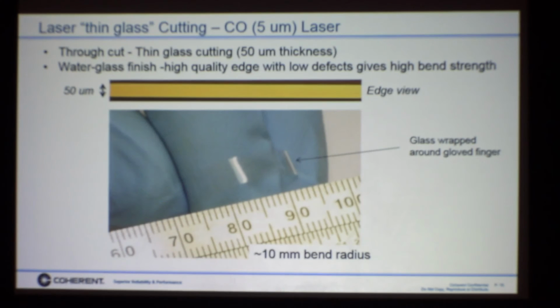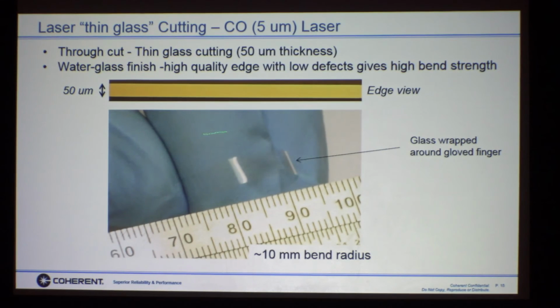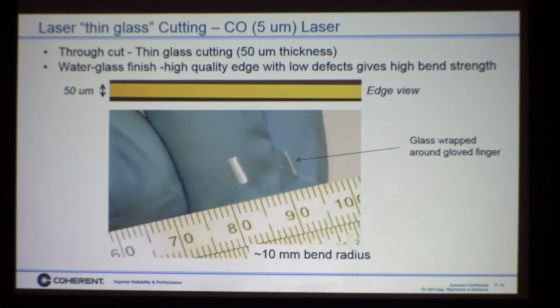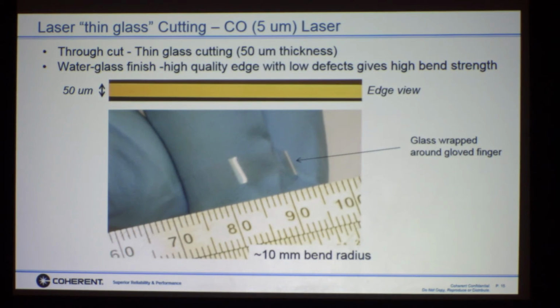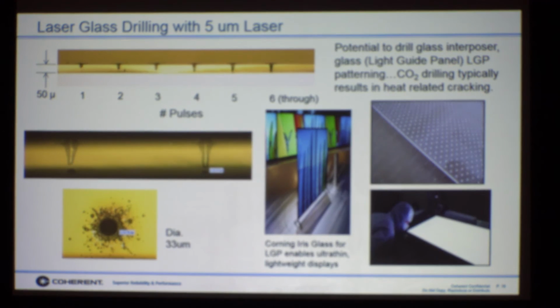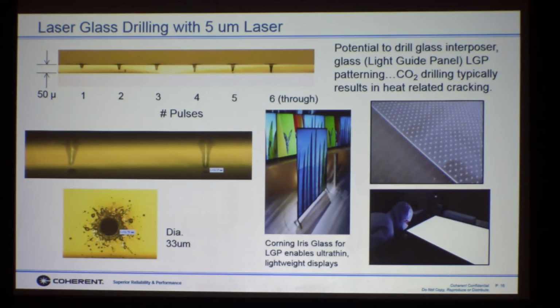Okay, so having this defect-free, and you can see there's another picture of it, what they call water glass finish. There are no defects when you cut with a CO or typically with a CO2 laser. So the defects are immeasurable in that case. Very strong. Another thing we can do with the CO laser, again, because of the 5 micron wavelength and the penetration, the absorption or lack of absorption in glass, is we can drill holes, very stable holes.